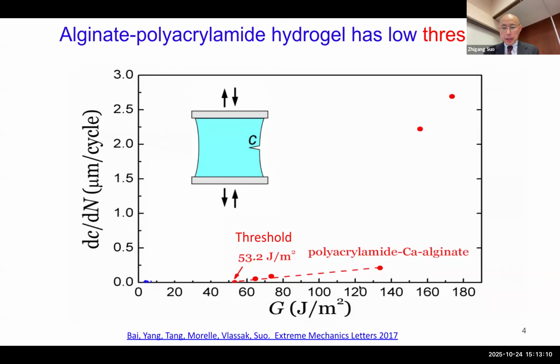So even at, let's say, pick up a number, let's pick this 160 number, even at this low value, you still get a crack growth. This C is a crack length. The vertical axis is growth per cycle. You get about a few micron per cycle growth of this crack. Now, this material is not very useful. 2 micron per cycle, after 1,000 cycles, you have millimeter cracks, right? So this is called a fatigue crack, or crack growth under cyclic loading.